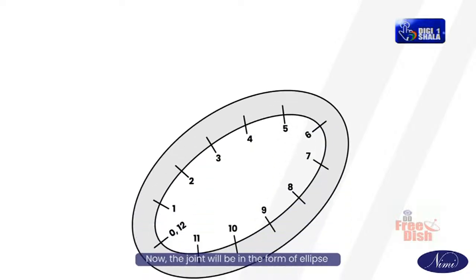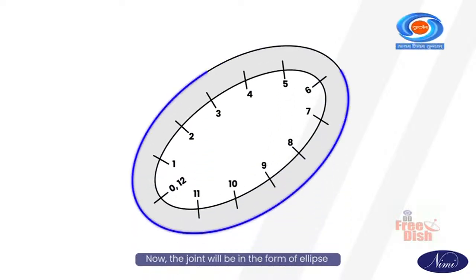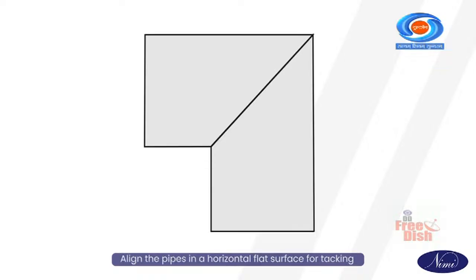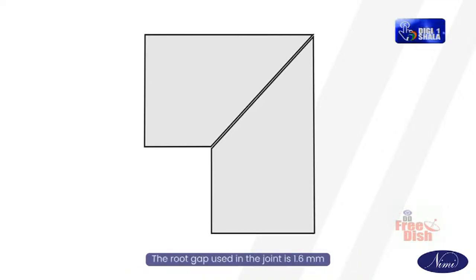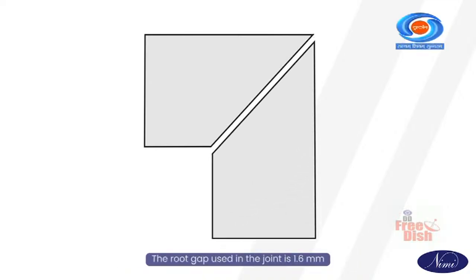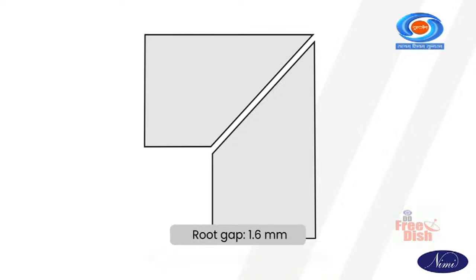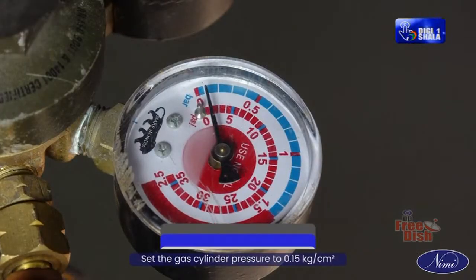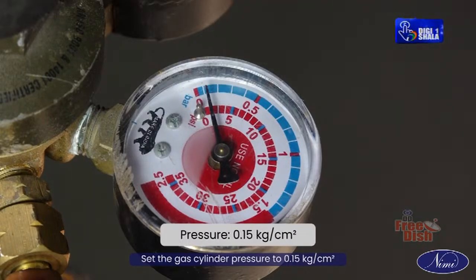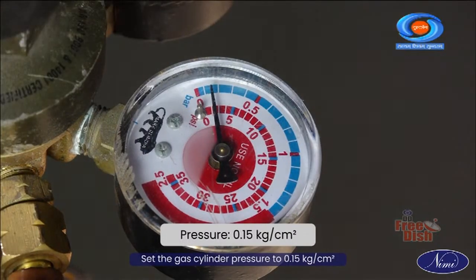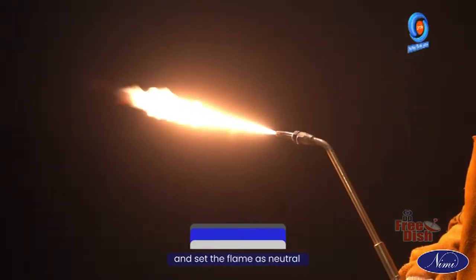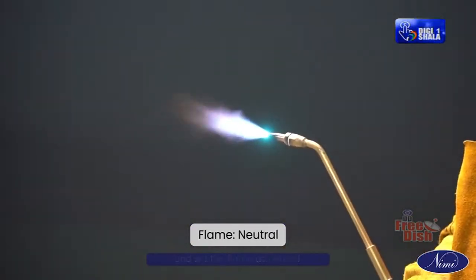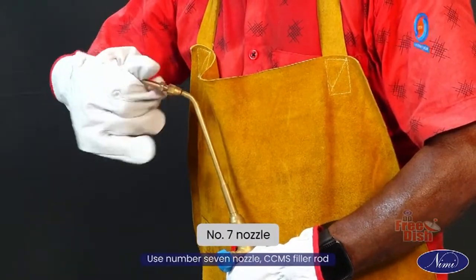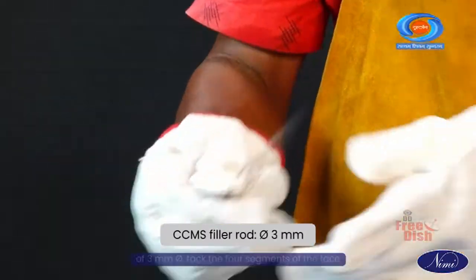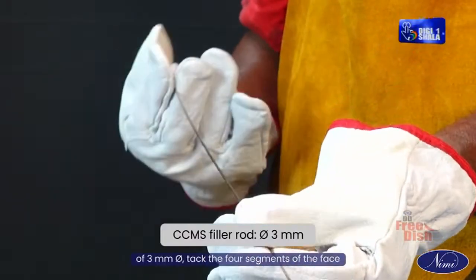Now, the joint will be in the form of an ellipse. Align the pipes on a horizontal flat surface for tacking. The root gap used in the joint is 1.6 mm. Set the gas cylinder pressure to 0.15 kg per centimeter square and set the flame as neutral. Use a number 7 nozzle and a CCMS filler rod of 3 mm diameter.